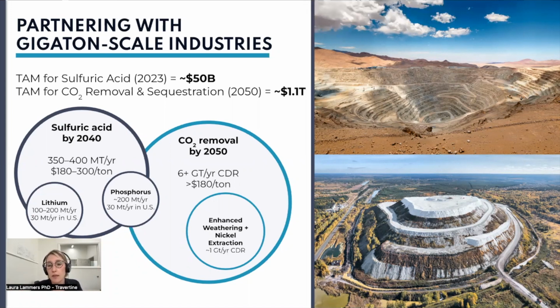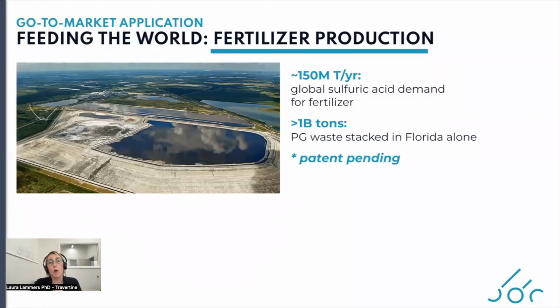And so these are some of the images of some waste feedstock here on the bottom, and one of the sources of, for example, ultramafic waste that we can use. And so our go-to-market application is processing what's known as phosphogypsum, which is a byproduct of phosphorus fertilizer production. Today, the conventional process for phosphorus fertilizer production is we take the original rock phosphorus, which is calcium phosphate, react it with acid, and you end up with a bunch of sulfate waste. What we can do is take this sulfate waste, turn it into solid calcium carbonate, taking CO2 from the air, and then return that acid back such that you can continue the process. And so we can end up with essentially substantially carbon negative fertilizers while at the same time producing very low carbon intensity, potentially carbon free cement products as well. And so we can take this feedstock, turn it into those precipitated calcium carbonates for use in blended cements.